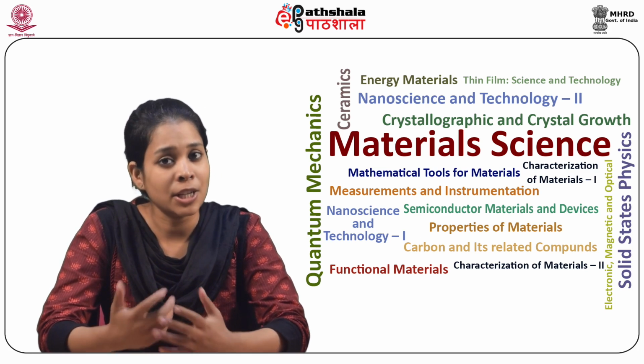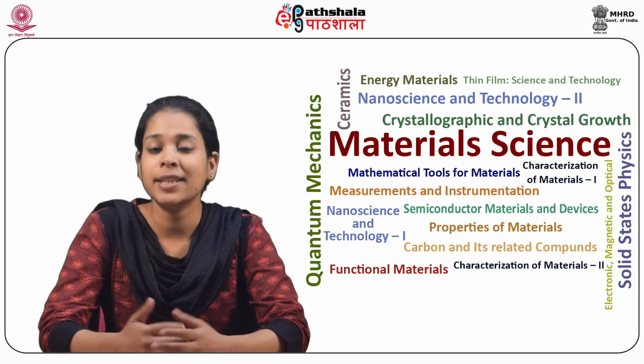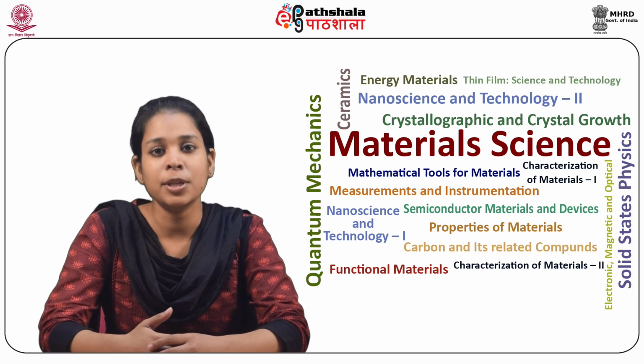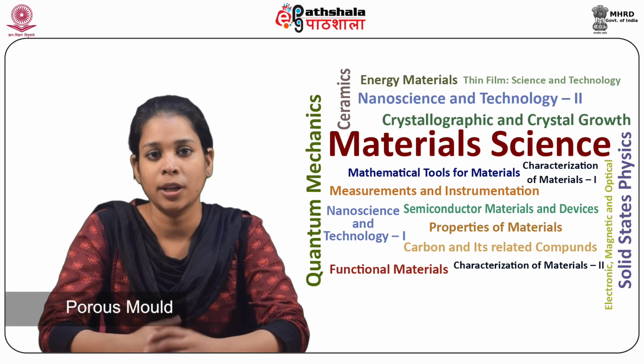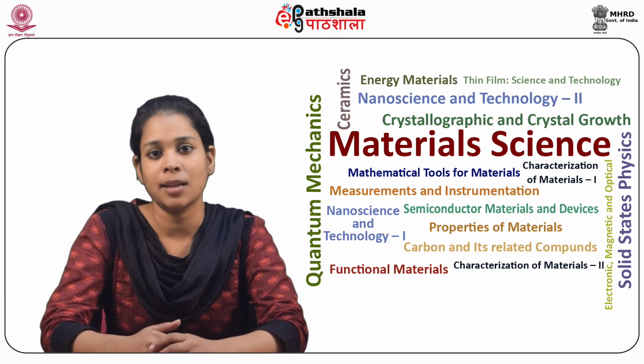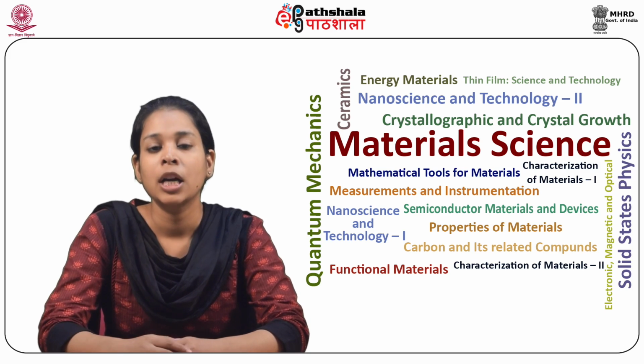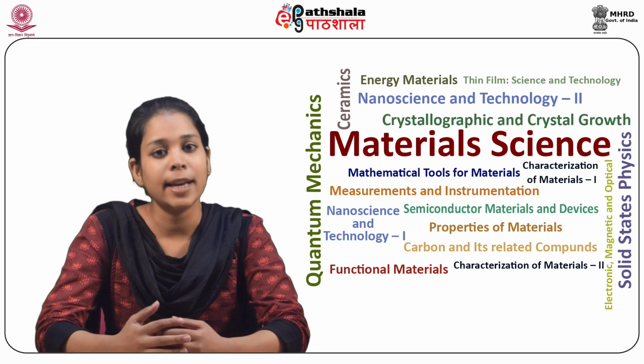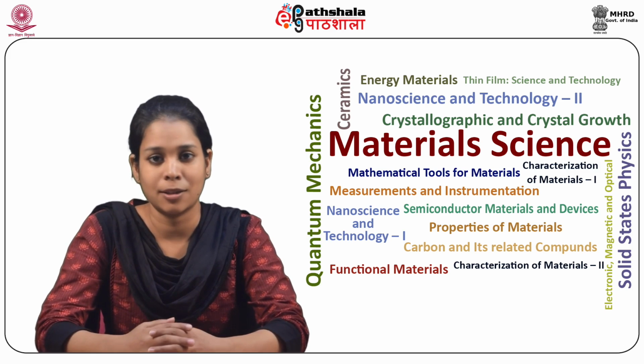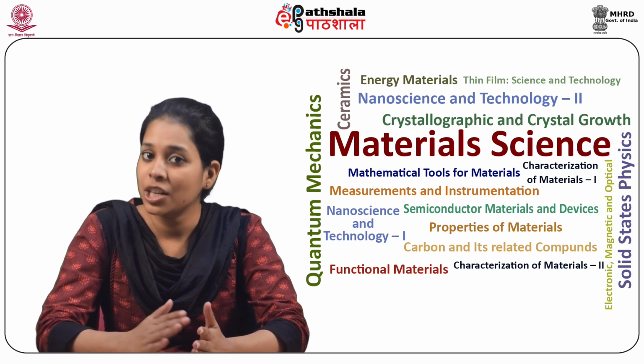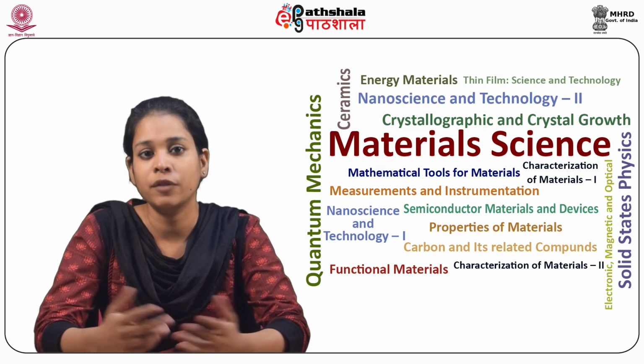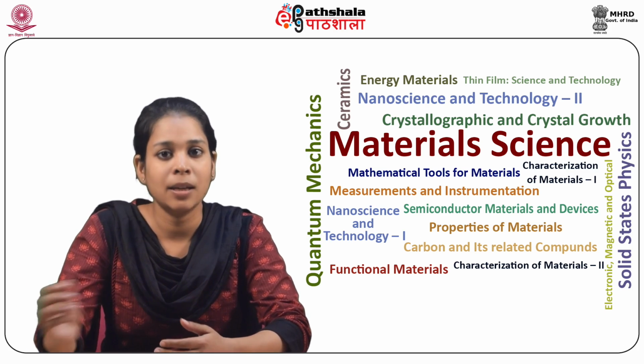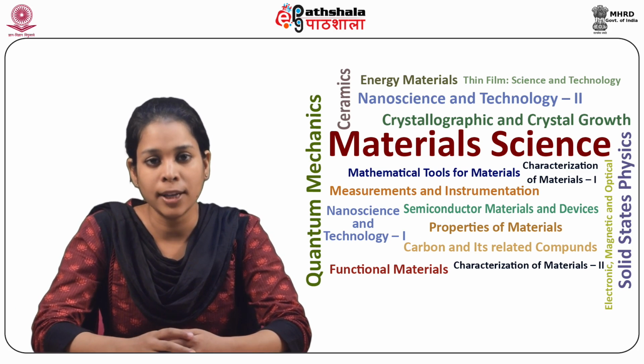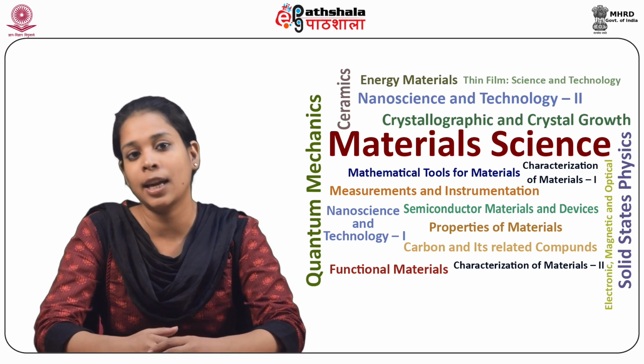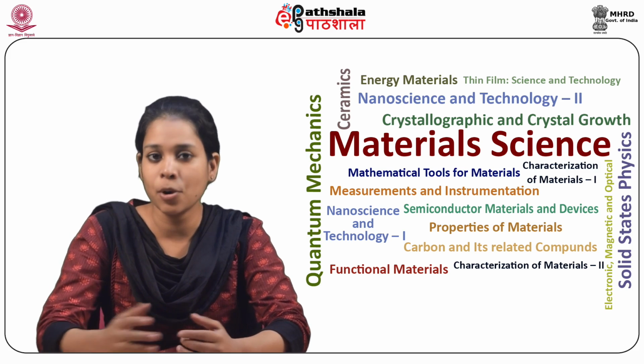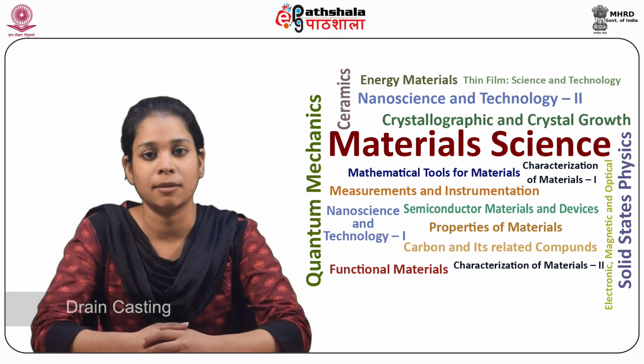So the process essentially consists of preparing slurry of the ceramic to be used and pouring it in a porous mold. The liquid is slowly sucked out through the pores of the mold due to capillary action to the external surface where it evaporates. A cake is formed adjacent to the internal surface of the mold and the remaining slurry can be poured out of the mold after the required thickness of the cake has formed. So this complete process is called drain casting.